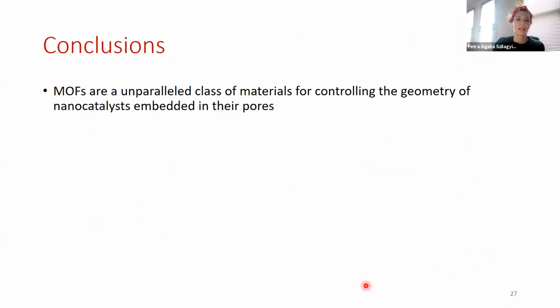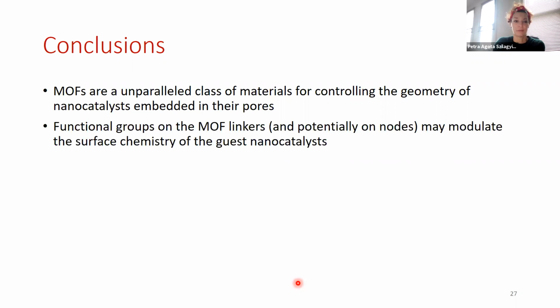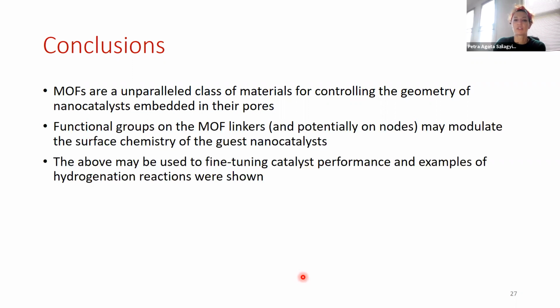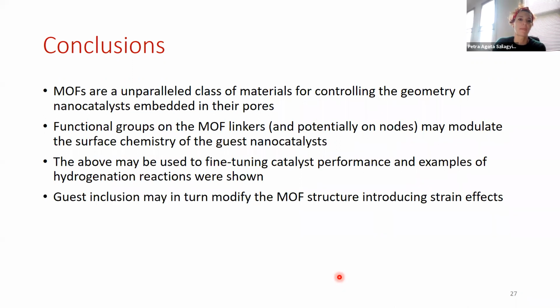So just to conclude, I hope I showed you that MOFs are a class of materials that are really quite interesting for controlling the geometry of nanocatalysts when we use them as templates for the nanocatalyst growth. And the functional groups on the MOF linkers, but as I said, they can also potentially be added on the nodes, may modulate the surface chemistry of the nanocatalysts. And all of the above may be used to fine-tune the catalyst performance of these composites, and I showed this in a few examples of hydrogenation reactions.